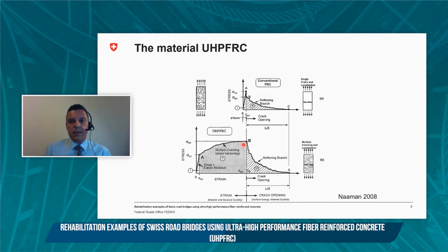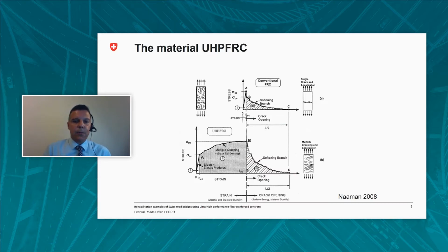However, the macroscopic deformation is still uniform and can be expressed by the strain epsilon. This is of high importance for the sealing properties of the ultra-high performance fiber-reinforced concrete, as we will see later on. At point B, a crack localization occurs and softening behavior is observed. Now, ordinary concrete with fibers do not present strain hardening. A main crack is formed, followed by